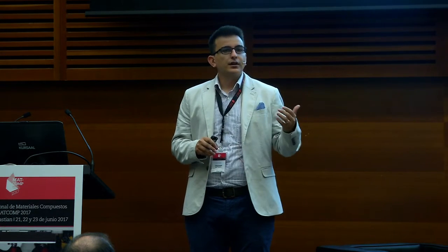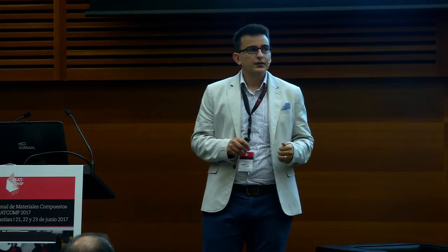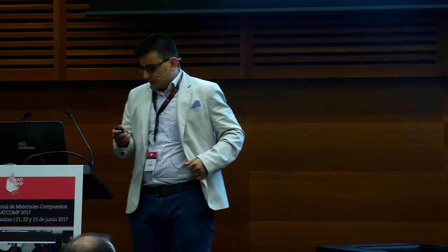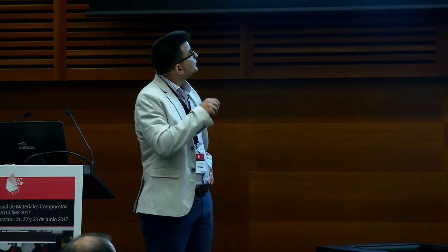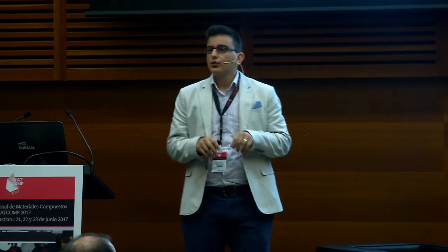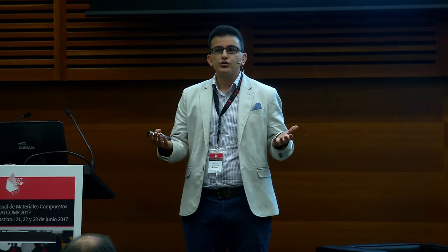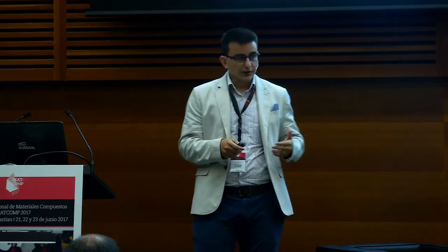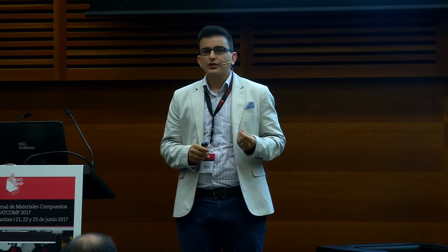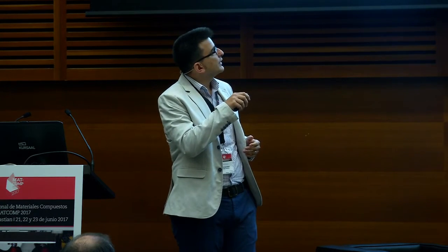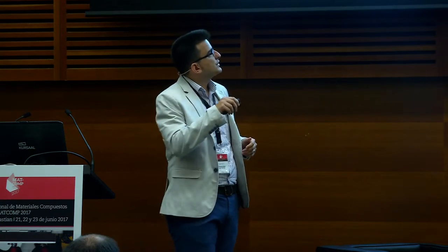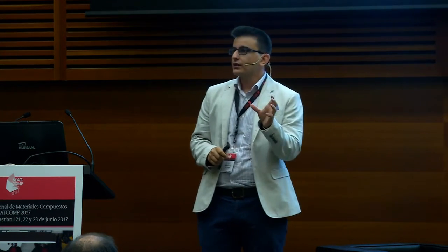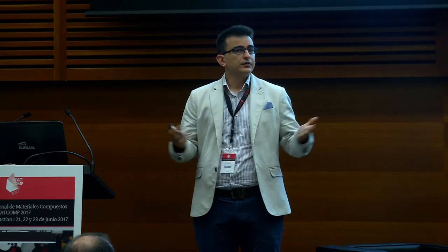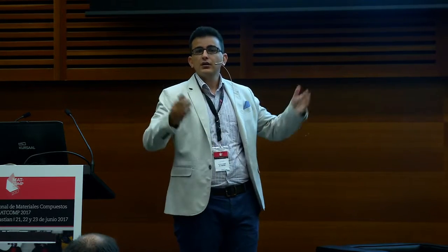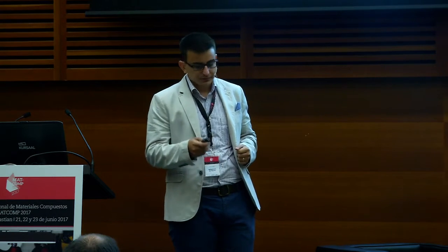So with the pultrusion process, we have really high fiber volume content, up to 70, even 80% by volume. So in pultrusion process, the fiber reinforcements are pulled through a resin bath or a resin injection chamber, in which the fibers are obviously impregnated. And then the wetted out fiber reinforcements enter heating or forming die, in which the matrix material changes its state from liquid to solid via a gel state. So at the end of the process, with the help of a saw mechanism, the product is cut into desired length in meters. So in principle, we can manufacture kilometers of profiles using this efficient process.